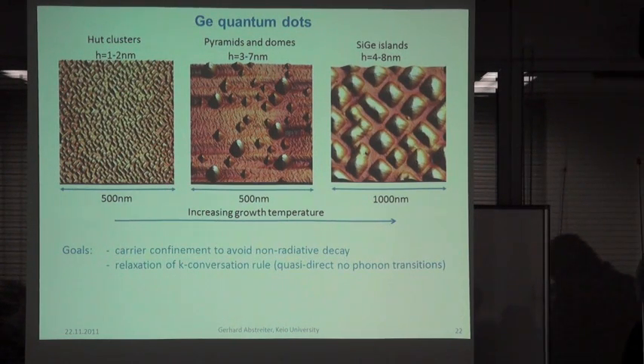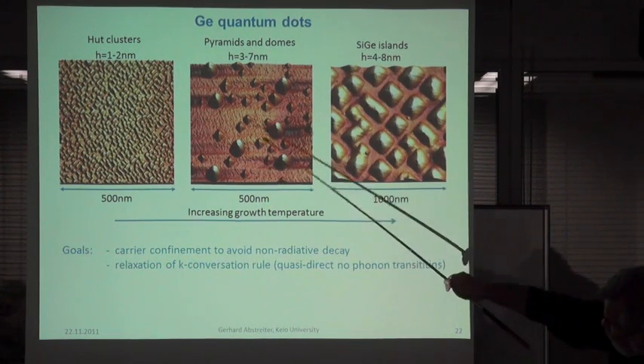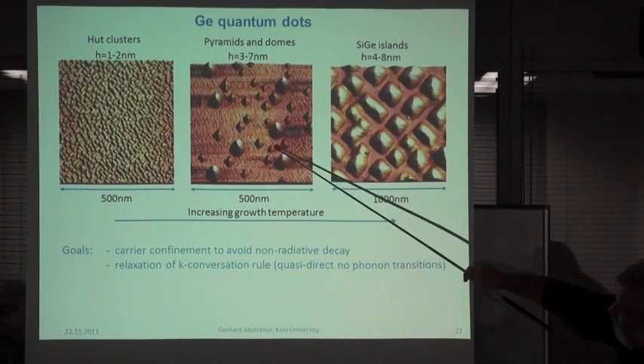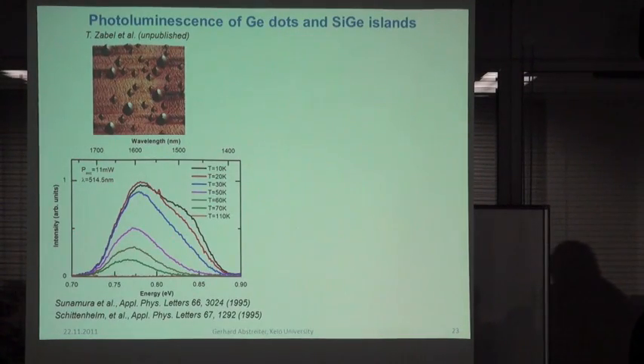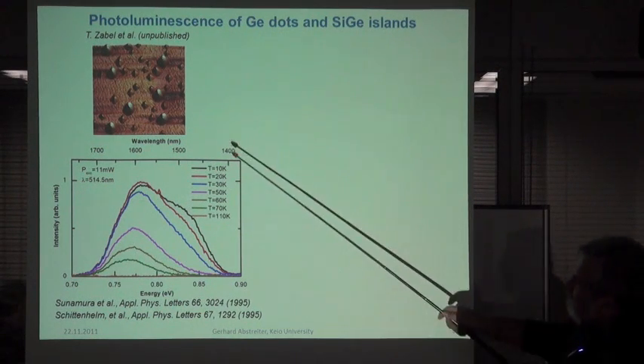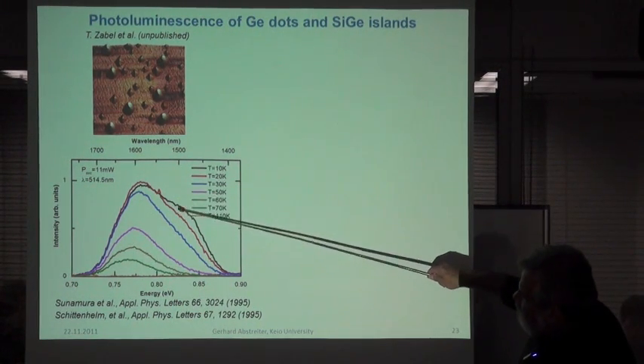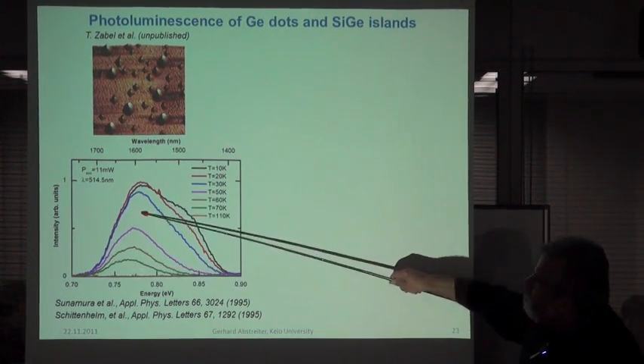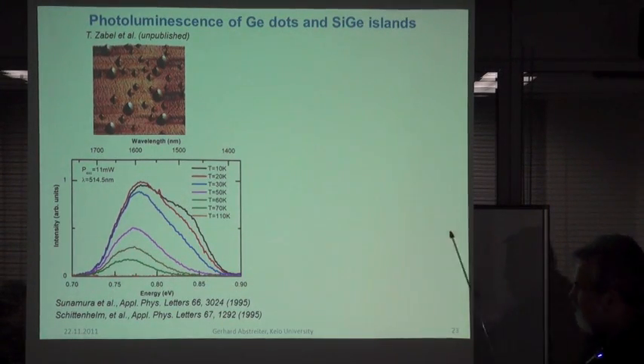So you get the electrons also into these islands and have more spatial overlap, and in optics you win due to the excitonic effect in oscillator strengths. So we are at the moment trying to work with this, but most of the work is done with these pyramids or domes. Now if you look at the luminescence of such pyramids and domes, you see this bimodal behavior a little, but very broad, inhomogeneously broadened because of different sizes.